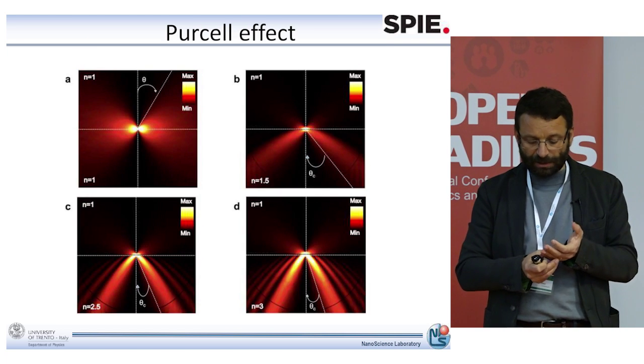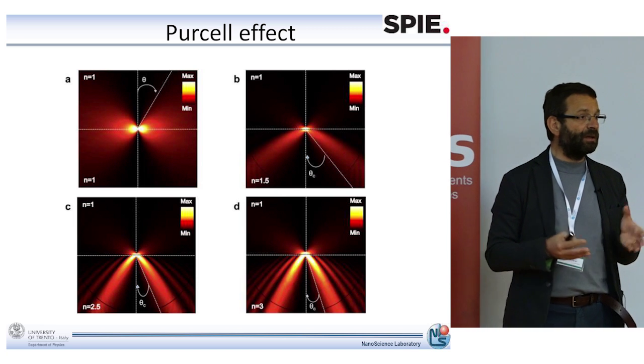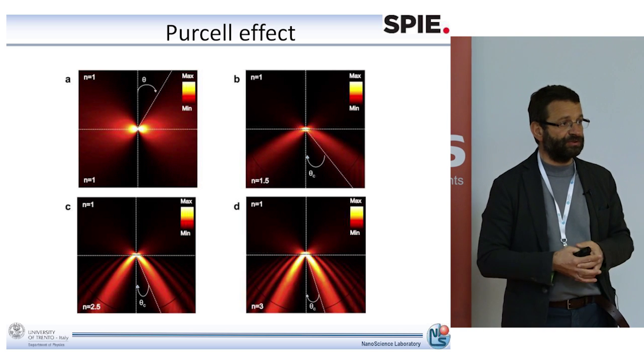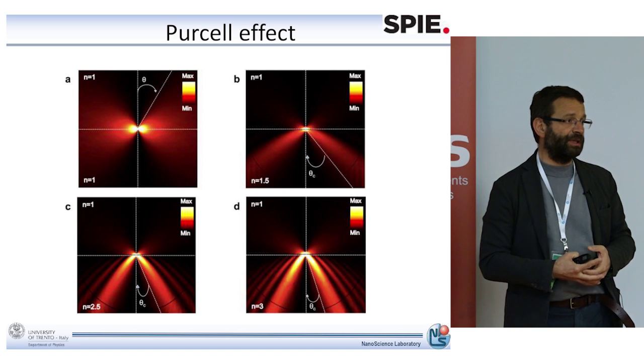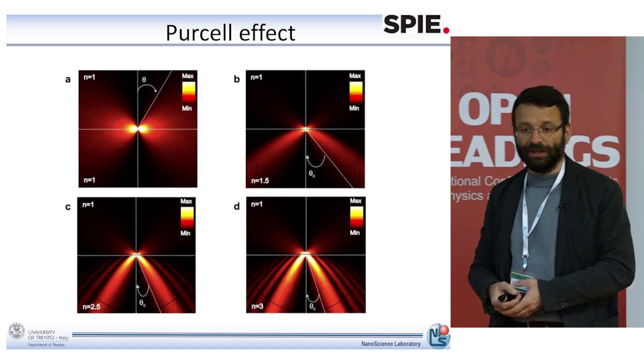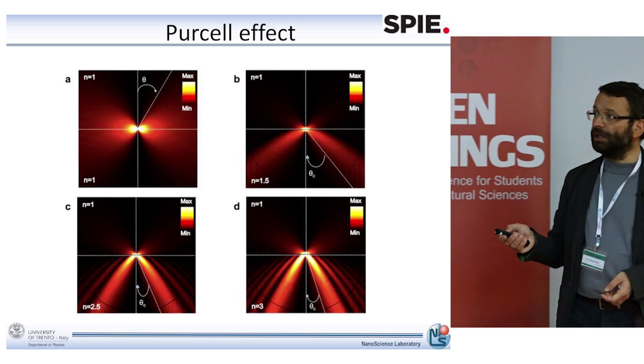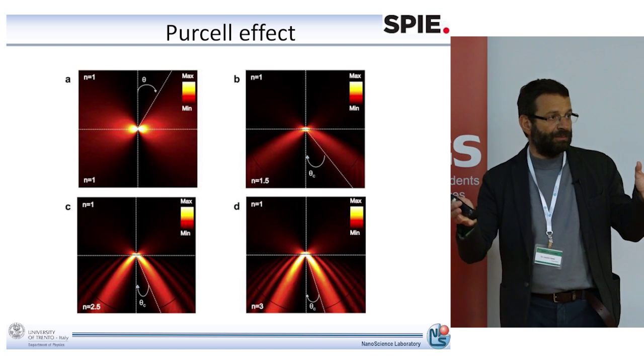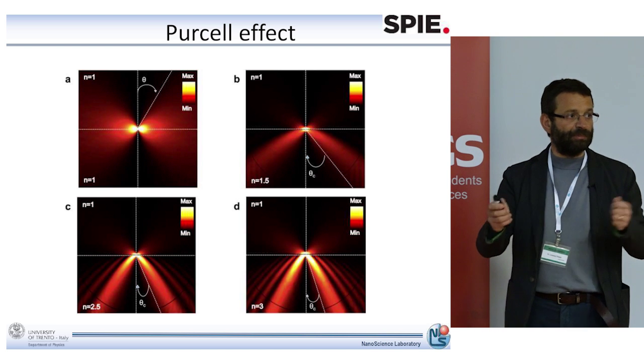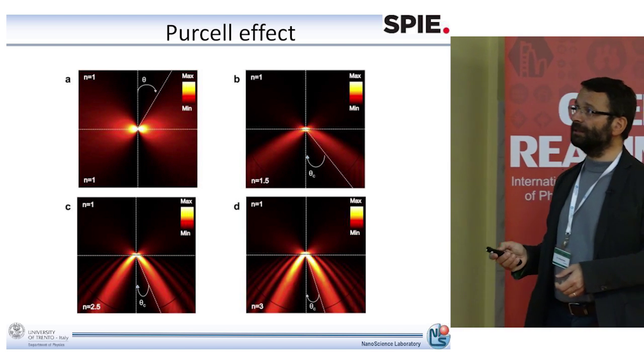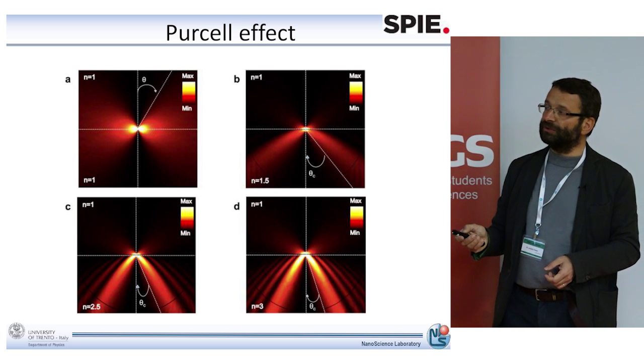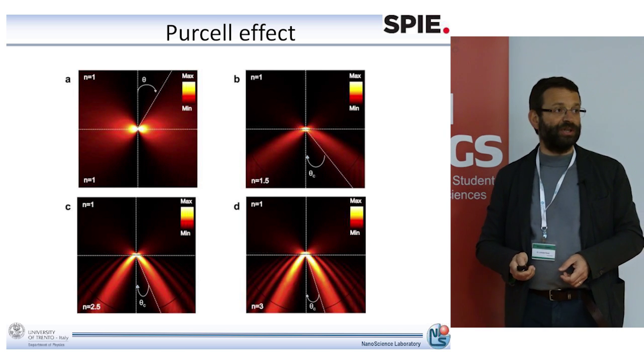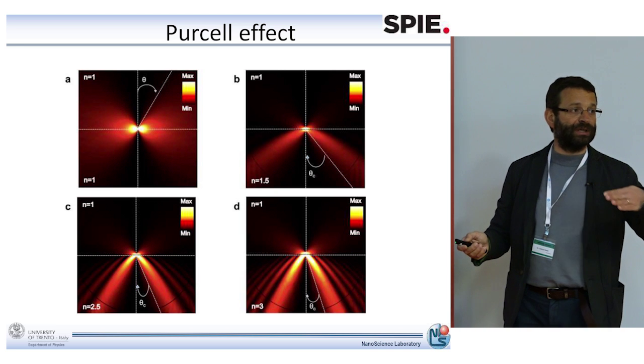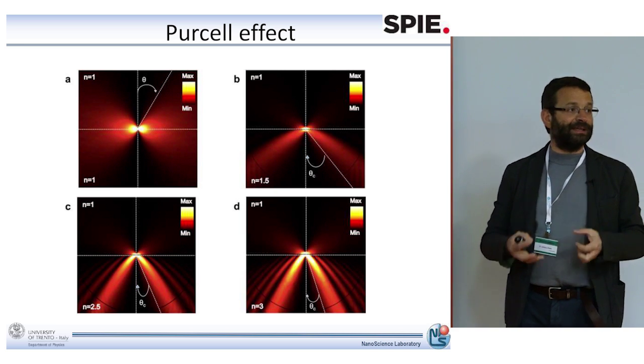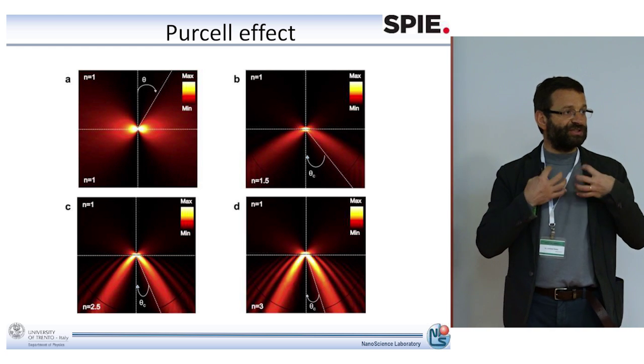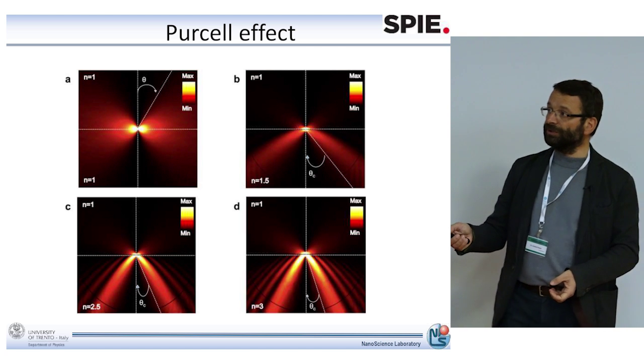The probability to get photon emission depends on the material, but it also depends on the photon mode density of states. And if you change the refractive index, you change the photon mode density of states. So photons tend to go where the refractive index is larger. If you put a dipole in air, you get the typical emission of a dipole. Since the nanocrystals are more or less randomly oriented, we get the same intensity of light emitted to the upper region as to the bottom region. But now if we change the refractive index of the bottom region where the cell is, we can increase the quantity of light that is emitted towards the high refractive index region.